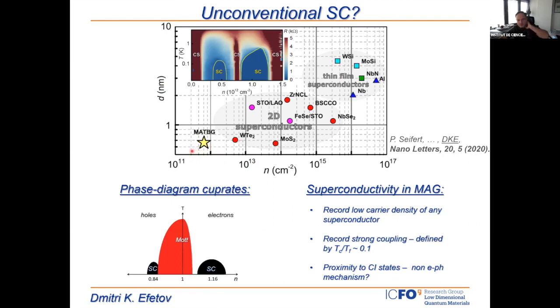And then also it is by far the lowest carrier density superconductor. The superconducting state is formed from a very low carrier density of electrons. This graph shows the carrier density on this axis, and you can see that the carrier density of magic-angle graphene is, for example, 3 orders of magnitude lower than that of BiSCCO or the NbSe2. So it's really special just by the sort of numbers it has. However, Tc here is not so low, actually.